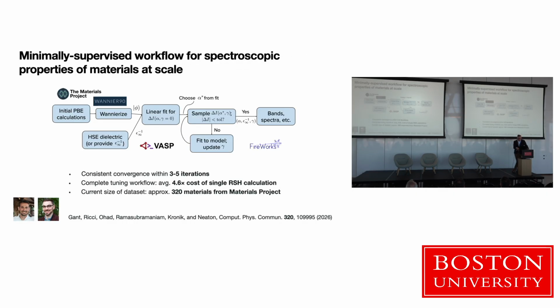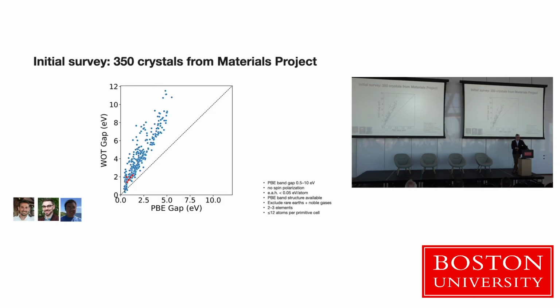So one of the things we've also done recently is to develop a workflow to generate the parameters per material in a somewhat, we call it minimally supervised way. It's not unsupervised. So we can generate these parameters pretty quickly in an automated fashion. And what we've done is look at about 320 of them. Now, we don't have experimental data for these, so we're just looking at their gaps. But this just gives you a little bit of a test; we just take structures from the Materials Project. And this gives you kind of a glance at what kind of data is coming out.